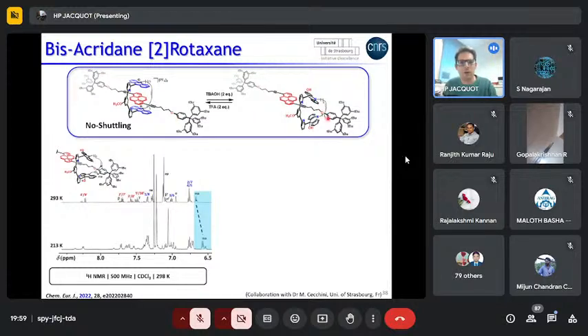If you have only 2 sets of signals, this comes from the macrocycle, which could be the trans and cis isomer of its olefinic bond. There were also only 2 sets of signals at low temperature. So we have no real dissymmetry of the 2 stoppers due to the motion of the macrocycle. So we have a free shuttling of the macrocycle along the dumbbell since there are no real specific interactions.